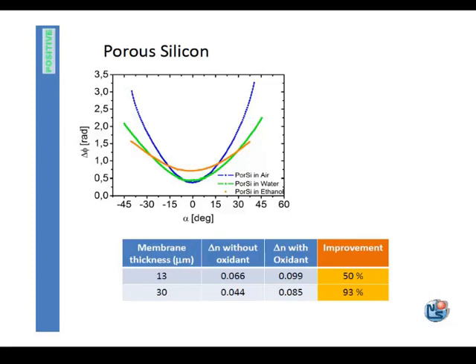Now we measure again the optical properties of our membrane. Here is reported one example of the analysis. In this case, we perform a variable angle spectrum, which is equivalent to a wavelength spectrum. And also in this case, you can see that the porous silicon response with air within the pore, or with water or ethanol, are different, but all these responses show the birefringence effect.